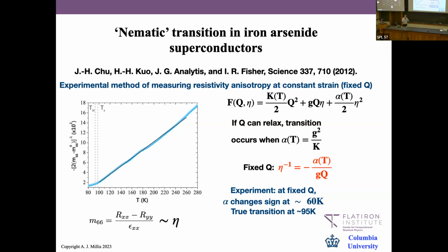Right, so if you have C4 symmetry, there's no anisotropy. If you put on some strain in a particular direction, it breaks the symmetry down to C2, you get some anisotropy, and you can ask how big of a change in the anisotropy of the resistance do you get? So that is a proxy for this coefficient, right?